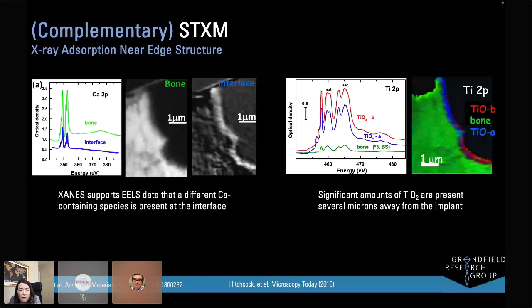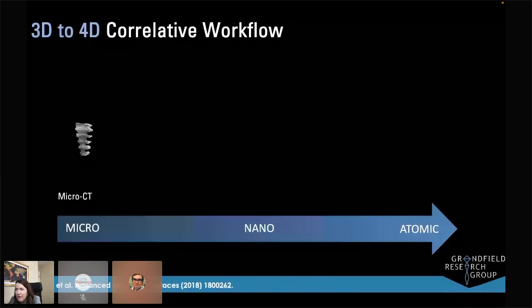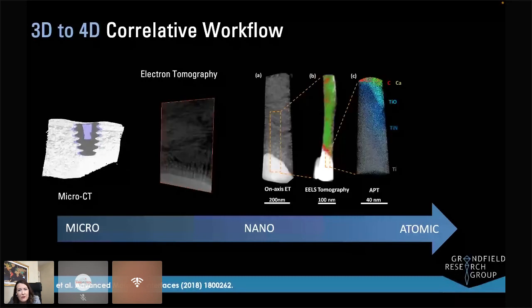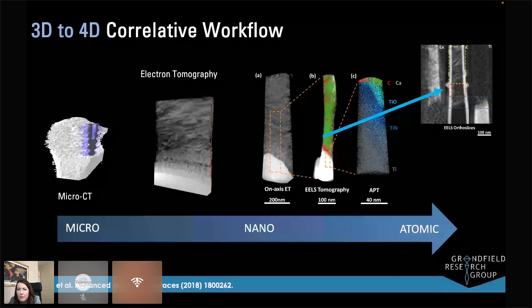It shows us a way to go all the way from the 3D scale, trabecular bone structure using micro-CT, where we see large-scale interactions of osseointegration, but by moving toward the nanoscale using electron tomography and EELS tomography, we start to approach information about the fibrillar structure of bone, where the collagen fibrils are located and where we have an afibrillar zone.